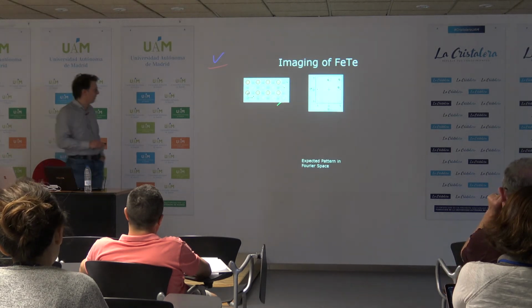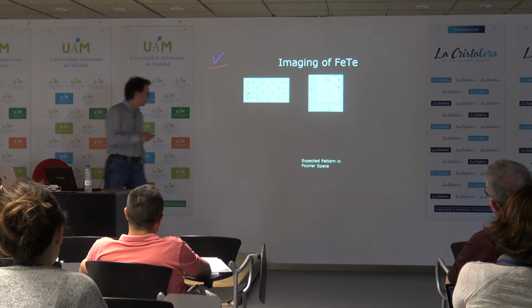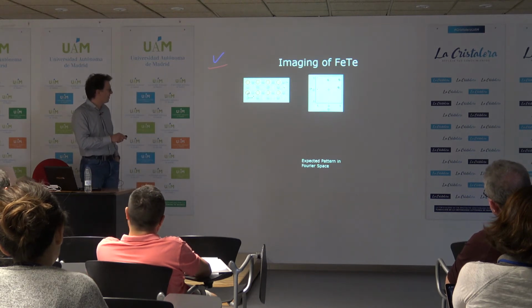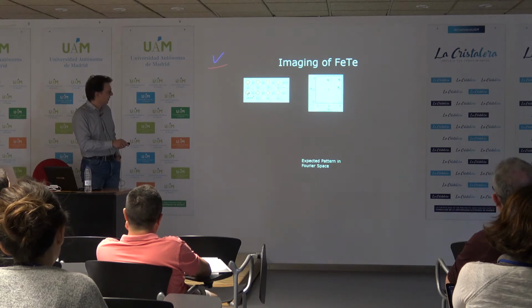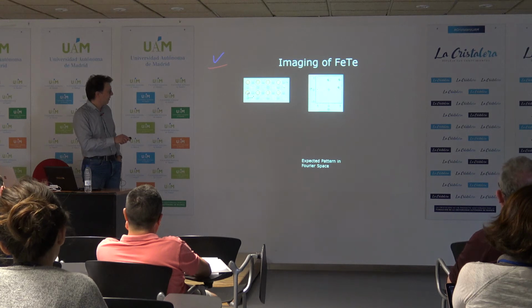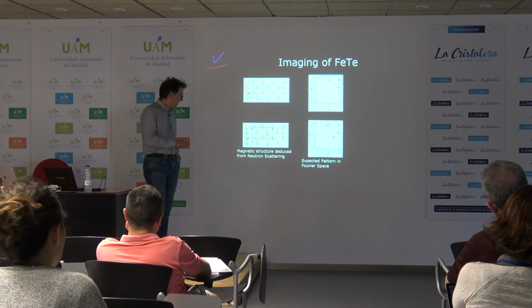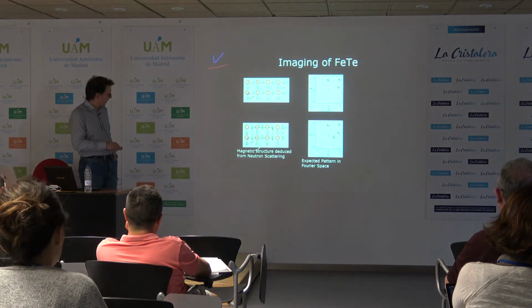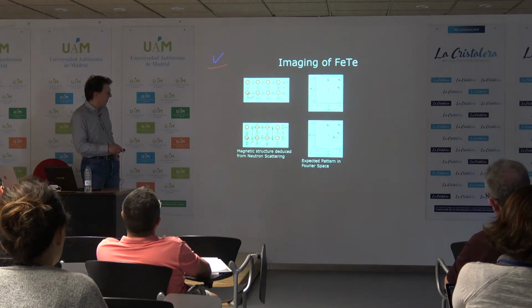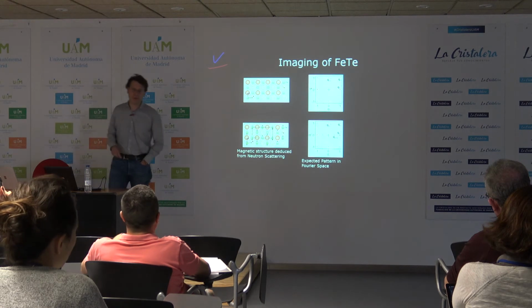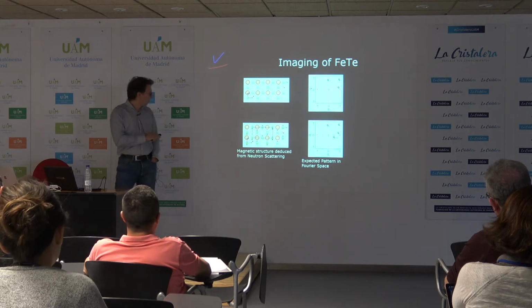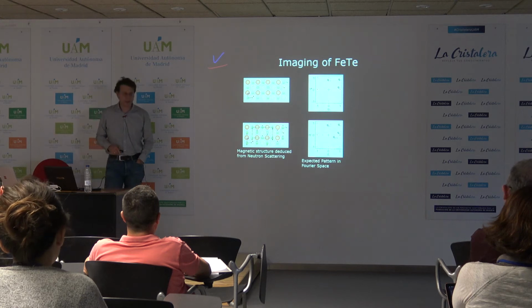So what we expect to see then is, if you like, a sketch of the structure in the top view. We should see these dark atoms here on a square lattice, and if we take the Fourier transform, we see these atomic peaks here predominantly, and then the iron lattice would be at these larger wave vectors here. Now, if we have a magnetic tip, then we should basically see the magnetic order, this bicollinear order here, and then in the Fourier transform of such an image, we should see additional peaks halfway to the tellurium peaks in the direction of the a-axis of this material.